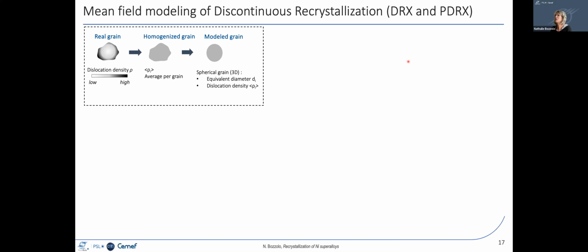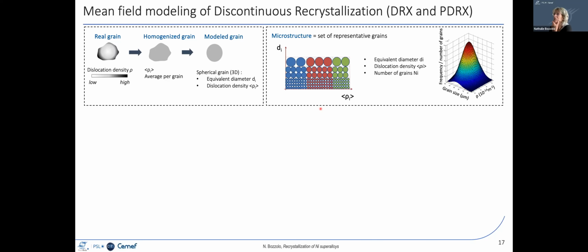They can be modeled with a mean field model. By mean field model, I mean we have to model the microstructure and the recrystallization phenomena. So let's start with the modeled grain. So a modeled grain would be a sphere with a given average dislocation density value. And a microstructure is a distribution of types of grains. A type of grain is defined by 2 parameters, a given size and a given dislocation density level. So this is the kind of statistical representation of the microstructure with grain categories characterized by a size and a dislocation density in this space.